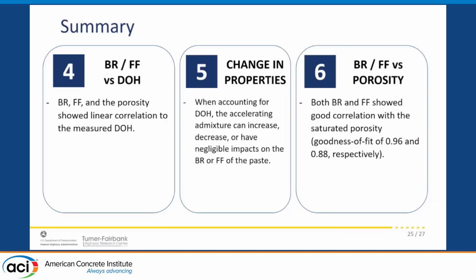And once we account for the degree of hydration, we see very limited effects of the admixtures at this dosage on the microstructural features of our cement paste.